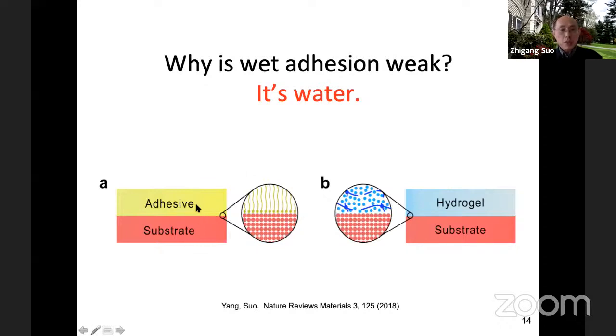So if you use a dry adhesive, such as epoxy or any plastic, to bond with aluminum—dry, right—then every atom really forms a bond, even though the bond itself could be just a very weak bond, like a van der Waals interaction. But everyone shares the load. Democracy—everyone shares the load, or even 50% shares the load, that's okay.